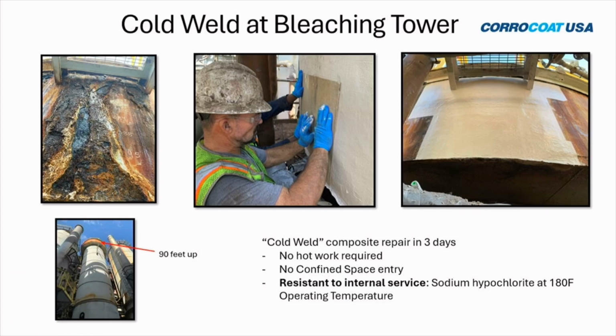So we were able to prefabricate a free film sample to the curvature of the tank, coated it on the back end. We vapor blasted, primed the surface with the coating, and then essentially glued it in with our coatings. As you can see, the finished product is going to last longer than the tank. They're never going to have to worry about that again.